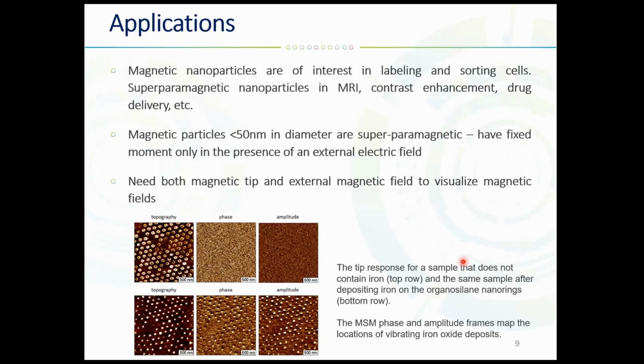What's interesting about trying to do magnetic force microscopy on such particles is that when you're dealing with magnetic particles that are so small in size, it turns out that the magnetic moment inside them is not fixed, but flips back and forth just due to energy from the environment at room temperature. So they don't have a fixed moment anymore, and they flip back and forth. In order to get a fixed magnetic moment out of these particles, one needs to apply an external field, either vertical or horizontal field, depending on the configuration of the system. And it's only after you do that you can hope to get a signal in an MFM image.